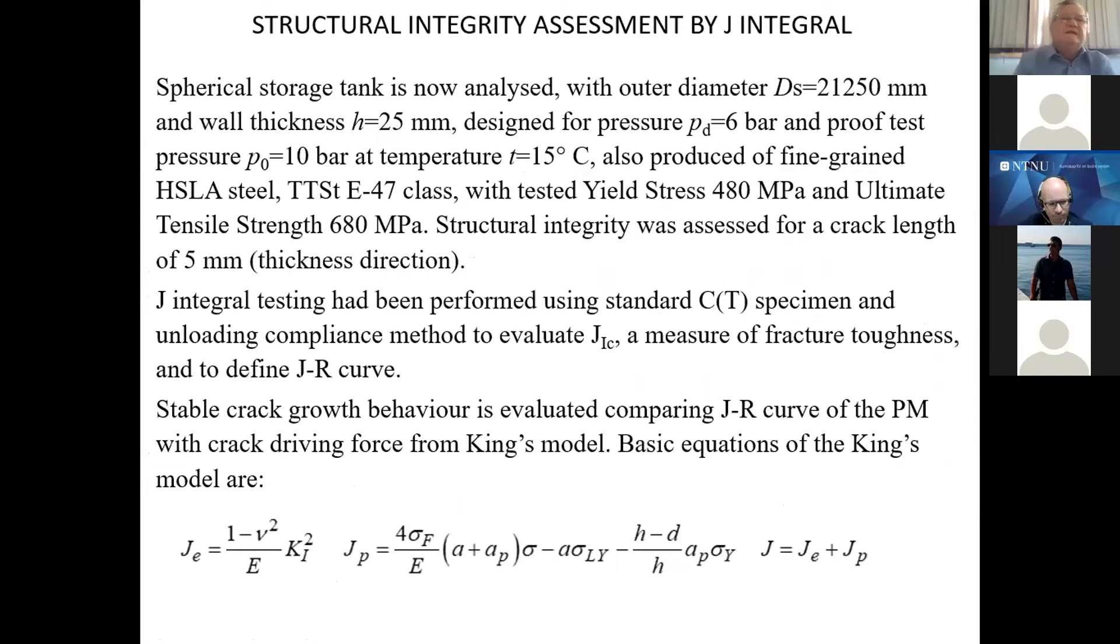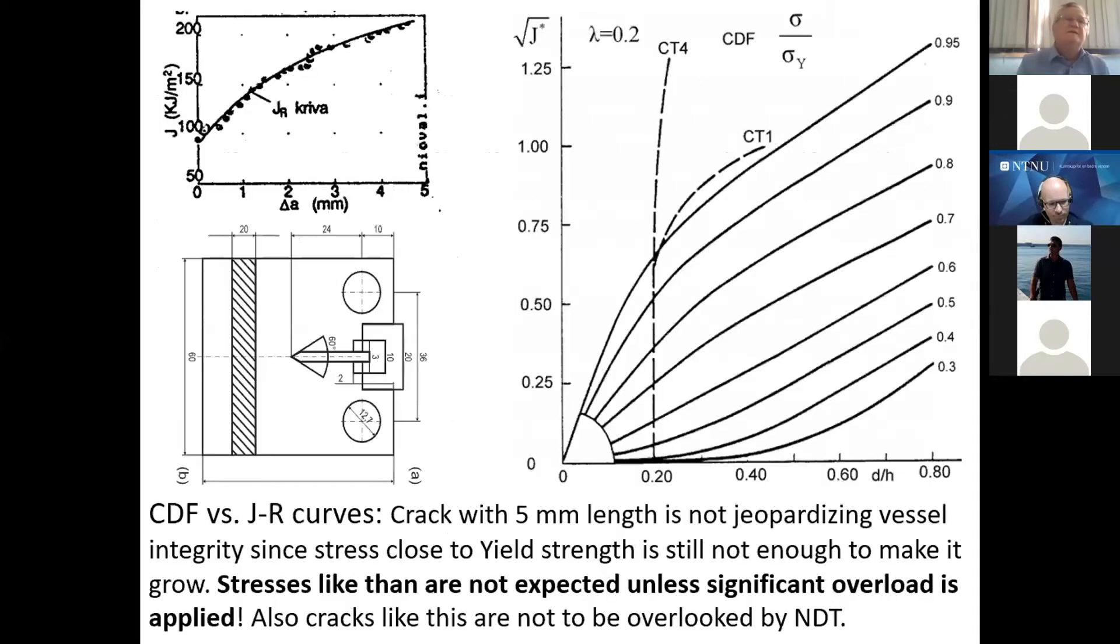More concretely, one storage tank that was analyzed, the data is given here. And we applied the same procedure and methodology as just described. So we used J-integral on one hand side as crack driving force, on the other hand side as fracture toughness. In the case of crack driving force, we used the so-called King's model. At that time, that was the best option. Nowadays, probably nobody remembers that model. But I think it's still usable for simple geometries like spherical tank really is.